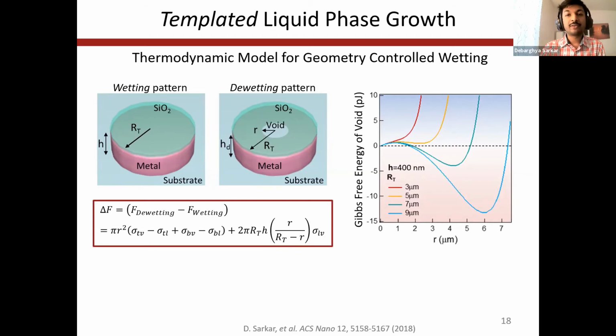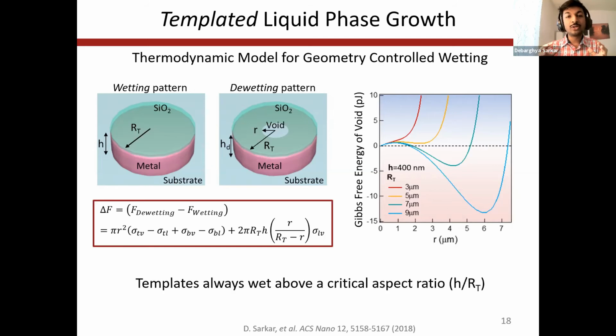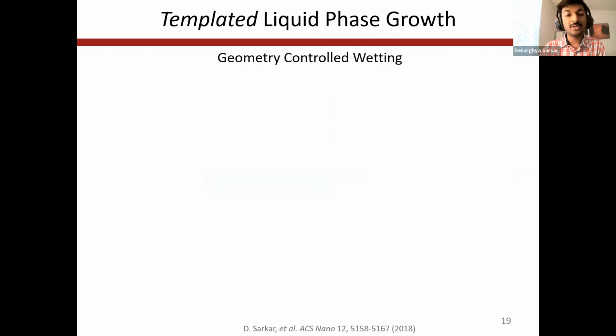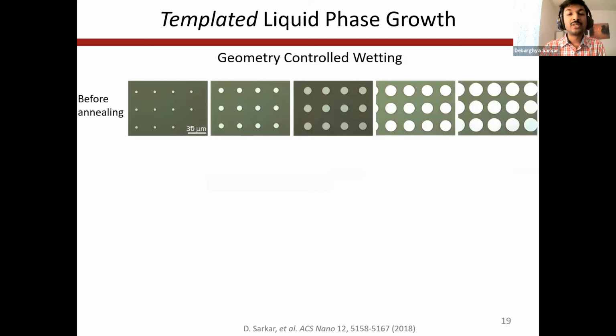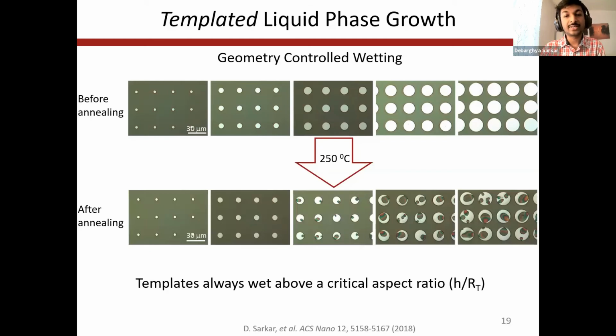Now, the major takeaway from this model for our growth purposes is that we would expect liquid metal templates to always wet a given substrate if they are patterned above a critical aspect ratio given by the height to the radius of the template. So to verify this, we performed an experiment where we patterned indium with the same thickness and different diameters. And we heated this up above the melting point of indium. And what we observed was that indeed, below a certain radius, indium templates stayed intact, whereas above that, they formed voids. And the size of the voids increased with the increase in the template radius, just as the model predicted.